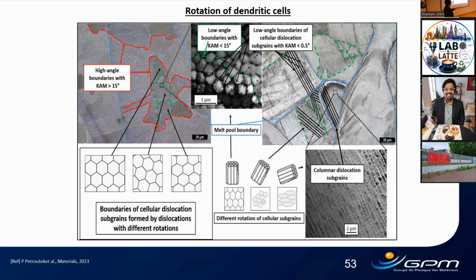And now when you ask whether it will change: yes, it will change. The reason is that many papers show that at the border of these colonies, or sometimes even on these walls, because of oxides or some pores or something like that, it could induce nucleation of cracks, and then it could be like an intra-dendritic fracture. So not about yield stress, but when it comes to fracture mechanics, I think certainly it will have a huge influence: the orientation of these colonies, in which direction they are oriented. If I'm not wrong, this is 316L also. Yeah.